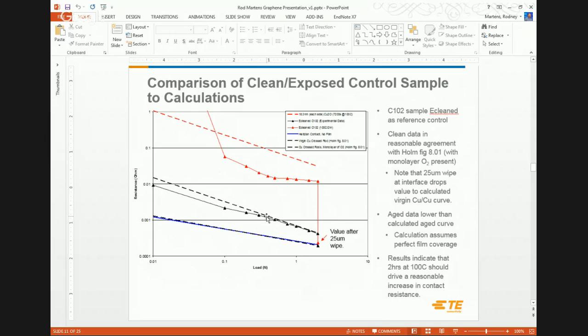Then I took one of those electrocleaned samples and aged it at 100 C for 2 hours to try to get up to what our calculated red dashed line was. We didn't quite hit it. It's a little bit off because the calculation assumes a perfect coverage of the film, no fracture, etc. So it didn't quite reach the 2 orders of magnitude, but it's definitely a bump in the signal, so we have something that we can measure.